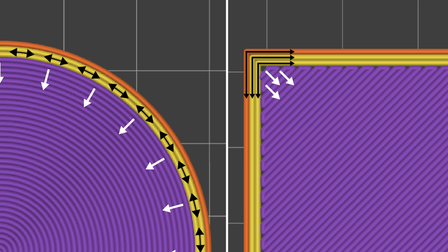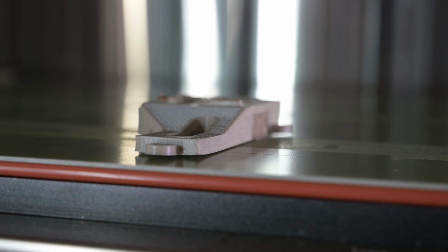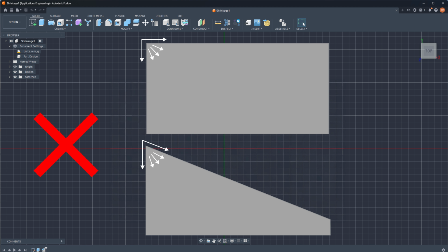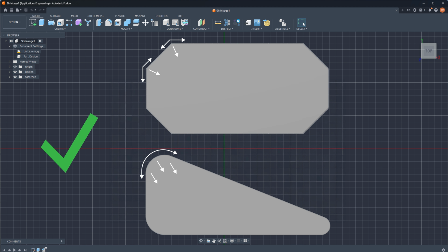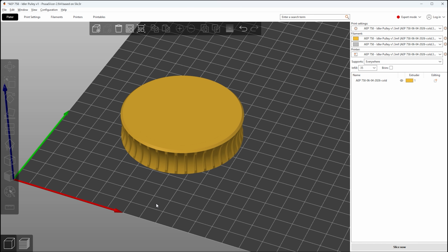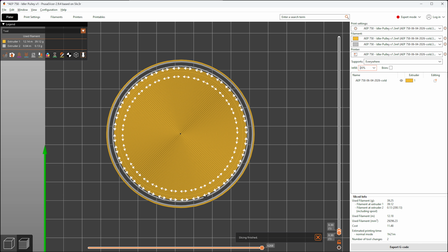Every new geometry and every design modification is going to come with its own unique set of challenges that you need to adjust for. Earlier, we mentioned that geometry determines where shrink forces develop, and this is where design changes become essential. Rather than eliminating shrinkage, you'll need to distribute those shrink forces over a larger area. Sharp corners and abrupt transitions concentrate that shrinkage in a single location, making them much more likely to warp or crack. Instead of corners, you'll want to use fillets, chamfers, rounded features, and simplify the geometry to spread those shrink forces throughout the part, making them significantly easier to manufacture.